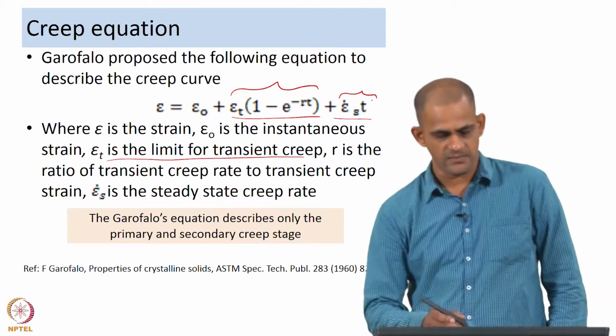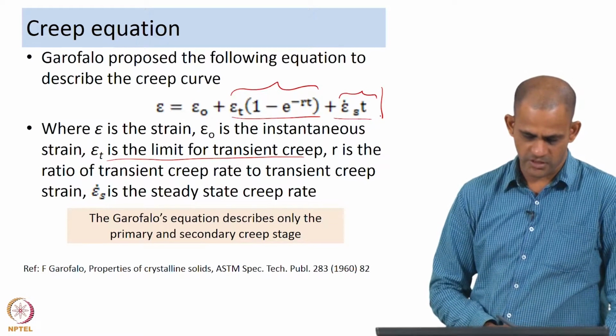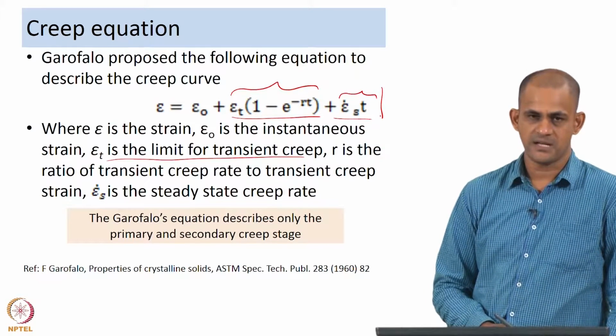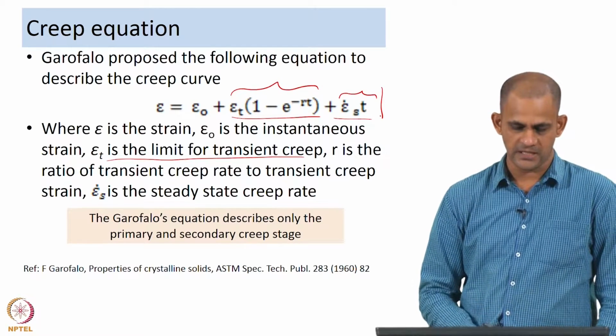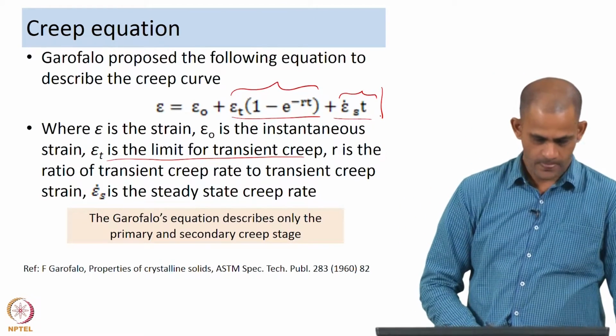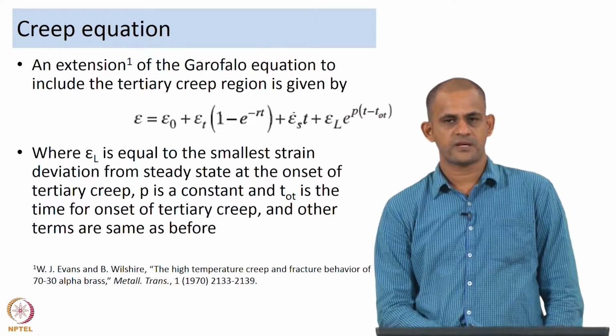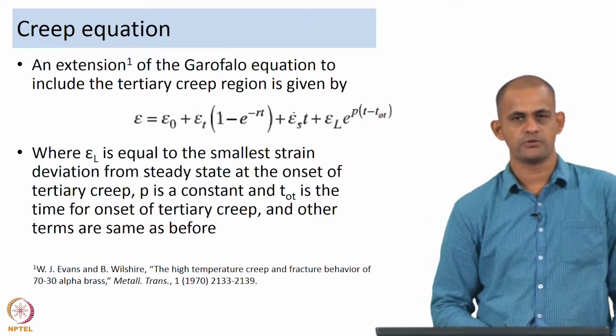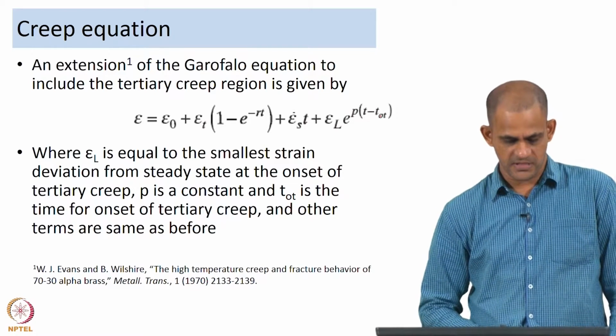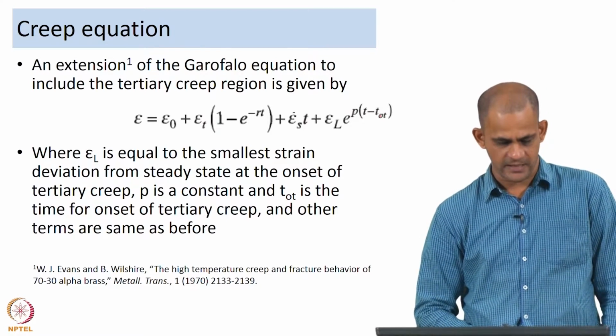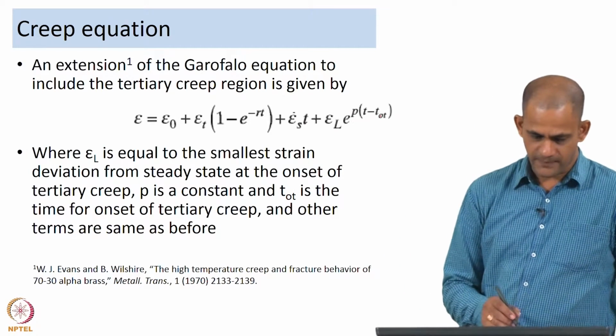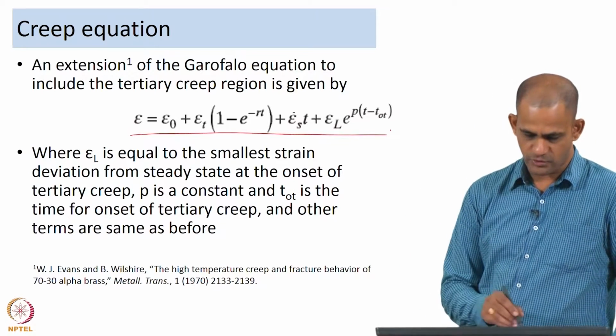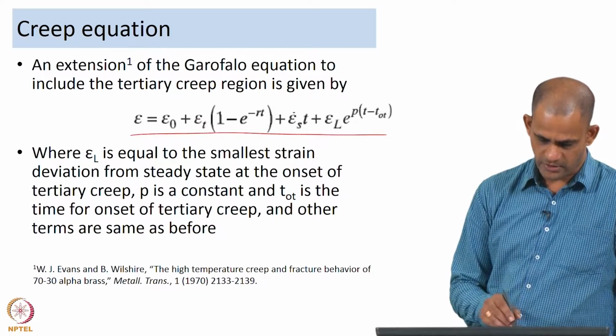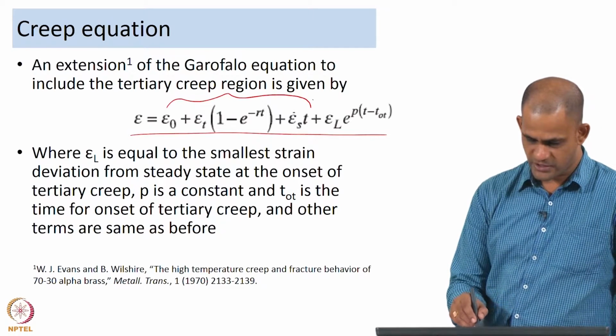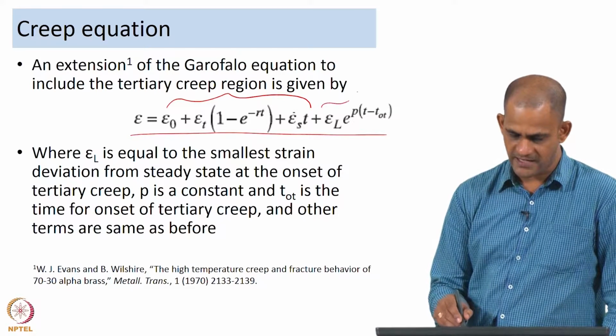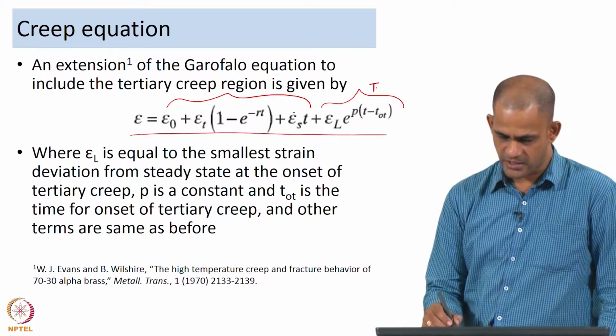However, what is very clear from this equation is that the Garofalo equation is only describing the primary and the secondary creep stage, and it does not say anything about the tertiary creep stage. However, an extension of the Garofalo equation can be made to include the tertiary creep regime, and this was done later by Evans and Wilshire, who showed that the creep curve could be described by the following equation. So, you could have epsilon is equal to epsilon naught, and up to this point it is the Garofalo equation, and then they added an additional term for the tertiary creep regime.